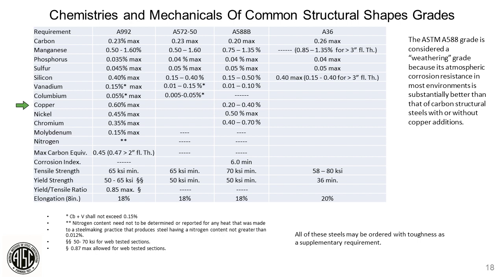And you look at nickel, again it's residual in all the other ones but 588. Sometimes we add that to get the corrosion index number up. And chromium, 40 to 70 on the next line. On A588, again, we've got to hit that range. We've got to hit 40 to 70 to get the properties of corrosion. Otherwise, we try to keep it down.